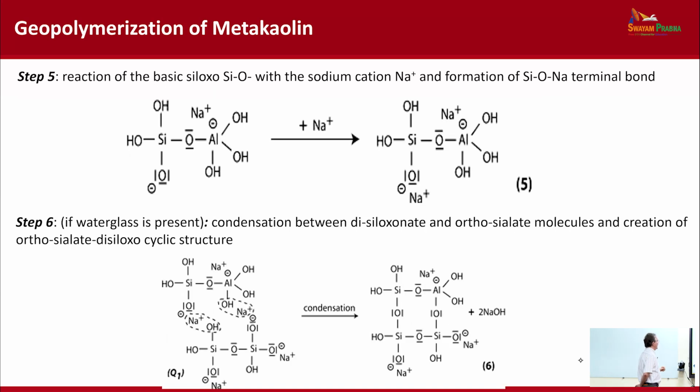And then you have finally the reaction of the SiO broken bond with the sodium cation, forming a termination bond. You can also have this besides forming OH groups. So this occurs spontaneously, occurs quickly, and by quickly I mean in the order of a few minutes at room temperature. Of course, you can use the temperature as a driver for speeding up or reducing the speed of these